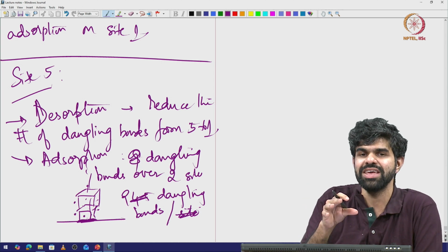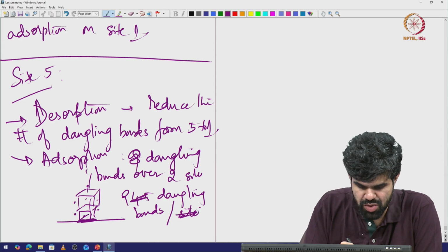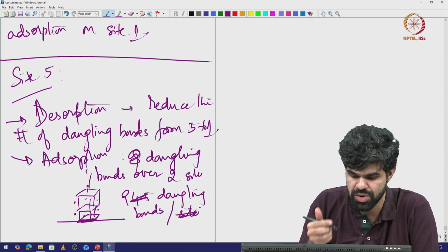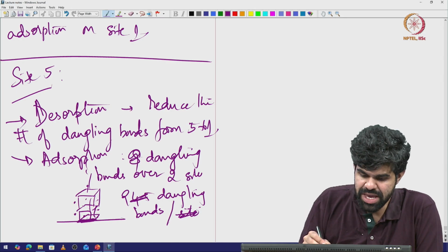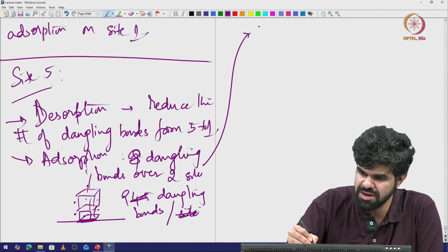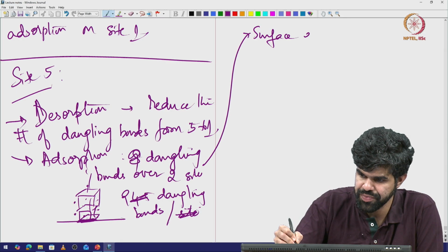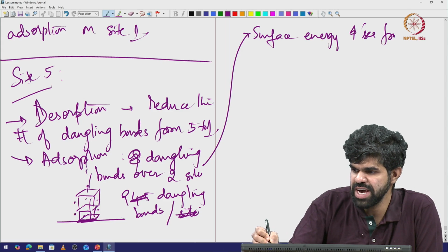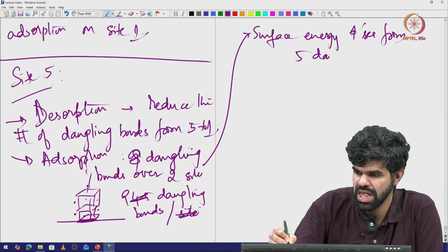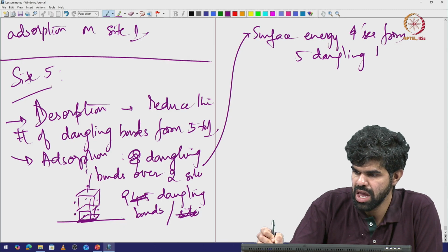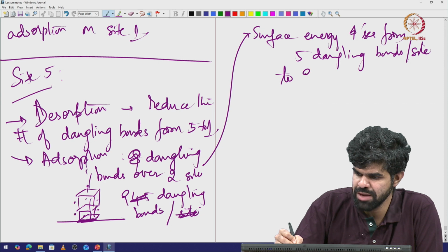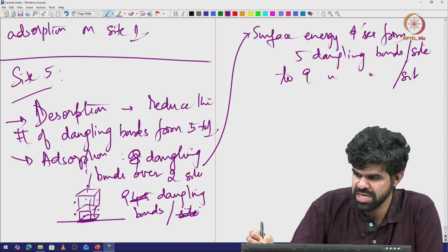The way you count is a bit different, because this is the only site of interest for me on the surface, whatever is on the surface. So here I have increased the surface energy from 5 dangling bonds per site to 9 dangling bonds per site.